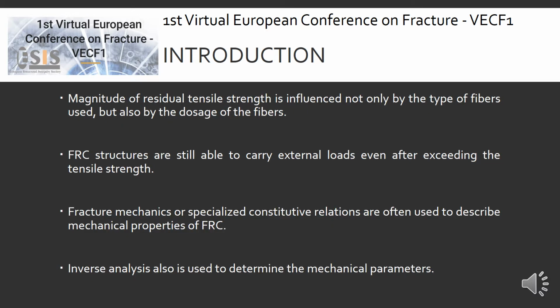The magnitude of residual tensile strength is influenced not only by the type of fiber used, but also by the dosage of the fibers. Fiber reinforced concrete structures are still able to carry external loads even after exceeding the tensile strength. Fracture mechanics or specialized constitutive relations are often used to describe mechanical properties of fiber reinforced concrete. Inverse analysis is also used to determine the mechanical properties.